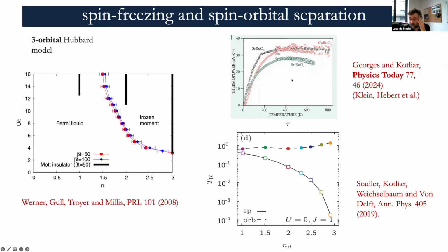This incidentally gives rise to striking evidence on strontium ruthenate, Sr2RuO4, and other ruthenates, which are another typical example of Hund's metal, which is extremely studied in this period, in particular by Antoine and his collaborators, but there are many other papers appearing. And this Seebeck data can be interpreted if you take into account that only the fluctuating spin contributes to the entropy. So this hallmark of Hund's physics also is seen to be extremized when you go towards the half-filling, which here again is 3.